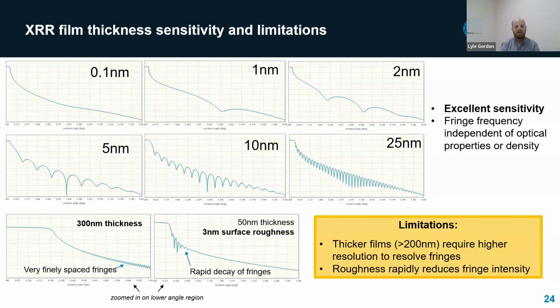So XRR works really well on very smooth films, like thin layers deposited on semiconductor wafers or coatings on glass. We can see here, this is a simulation for what would be a very nice case in the bottom center for a 50 nanometer thickness film, but just including 3 nanometer surface roughness, we can see that these fringes really rapidly decay. In this example, you could still fit the thickness, but you lose precision. There's not as many fringes. And if you have multiple layers, it'll become really difficult to extract all the properties because the fringes decay so quickly from the roughness.